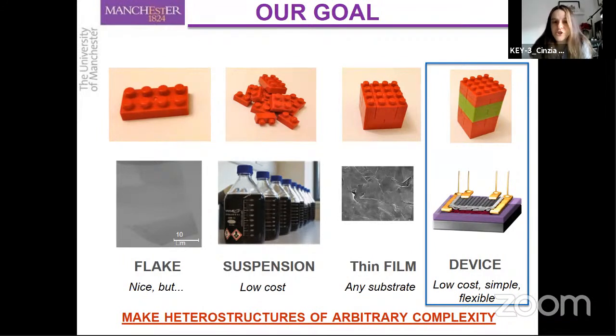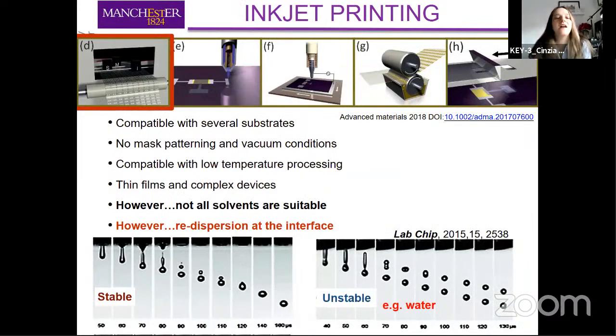And of course, those kinds of heterostructures can be fabricated with very simple techniques. And we have many approaches that have already been developed for organic electronics, so they can be easily extended to 2D crystals. And in particular, inkjet printing is a very attractive technique for fabrication of heterostructures starting from solution processed 2D materials, because as you can imagine, we can print very thin films, which will be suitable for flexible substrates, so will be compatible with flexible electronics. In principle, we can make those heterostructures on any substrate, on any location on the substrate, by simply printing different inks on top of each other.